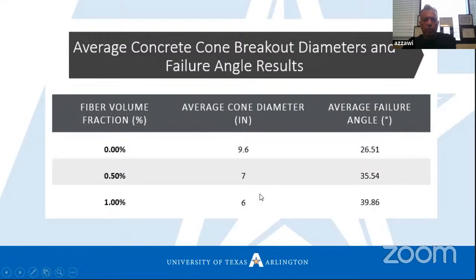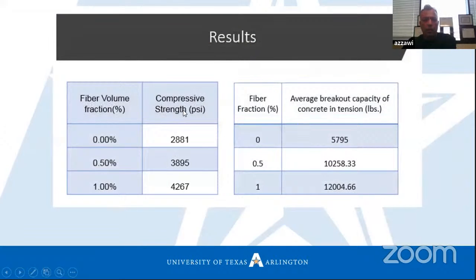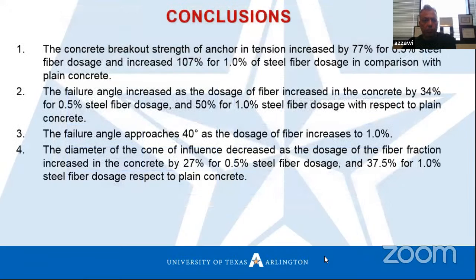We have a table here that shows us the average cone diameter and also the failure angle. As we see, the angle increases if we provide more fiber, and the diameter of the cone decreases as we provide more fiber compared with the plain concrete. These are the results. The average breakout capacity of concrete in tension, as you see, is a remarkable improvement.